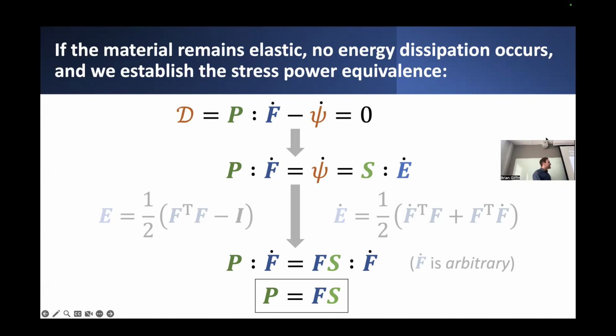Or in other words, we find at the end of the day, as a consequence of this argument of stress power equivalence between the rate of external work and the rate of increase in internal elastic strain energy, for that to be satisfied, we have to have this relationship between, in this case, the first Piola-Kirchhoff stress and, on the right-hand side, the deformation gradient multiplied by this stress tensor we've come up with, the second Piola-Kirchhoff stress. So we find this rather nice, succinct relationship between first and second Piola-Kirchhoff stresses. And obviously, we can take that one step further.